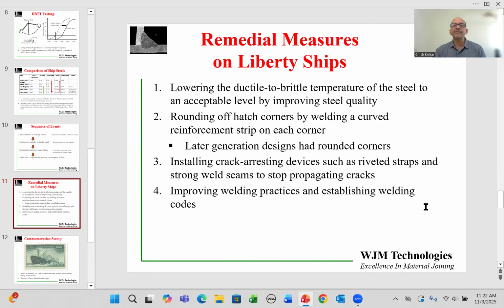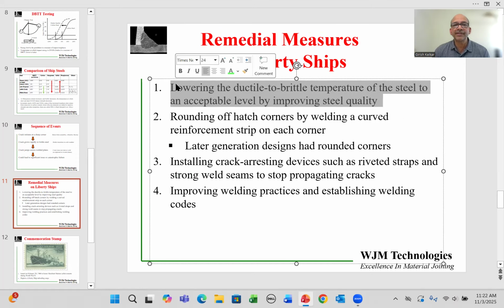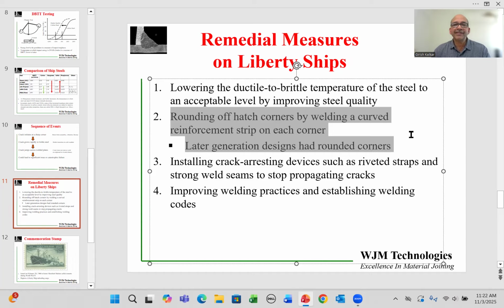So what were the remedial measures taken on the Liberty ships? First was to lower the ductile to brittle transition temperature by improving the quality of the steel. The second was to round off the hatch corners. Some of the ships were already made, so what they did is they put welded patches on all these corners to prevent the stress from opening up a crack at that location. Later generation designs already had round corners. Further, after or halfway through the Second World War, all the ships from there on always had rounded hatches and corners.